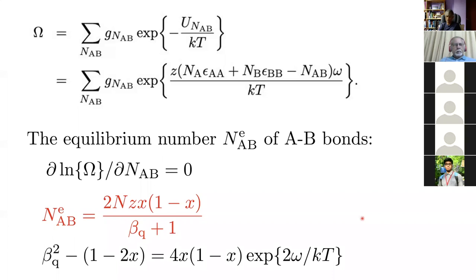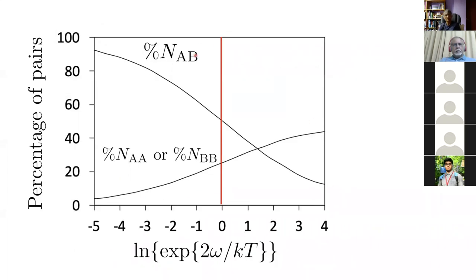Plotting this equation: the number of AB bonds varies with the enthalpy parameter omega, as do the numbers of AA and BB bonds. When we have an ideal solution — enthalpy term equals zero — the number of AB bonds is simply given by the probability of finding an A atom times the probability of finding a B atom; N_AA is proportional to (1-x)² and N_BB to x². But when we have a finite enthalpy of mixing, that is no longer the case.